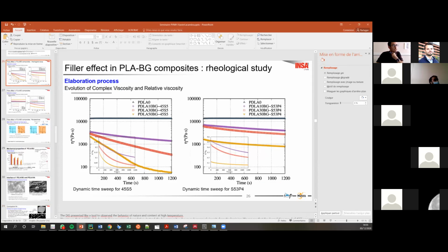So for slide 26, do we expect larger strains to enhance the degradation for a given formulation? You see my point here? If you increase the amplitude of the oscillation, do you think that it will help to degrade the polymer? I think that, as we can see in the extrusion process, we have an enormous shear rate in the twin screw, and it will accelerate the degradation. So in a nonlinear study, increasing the shear rate, maybe we could see this effect.